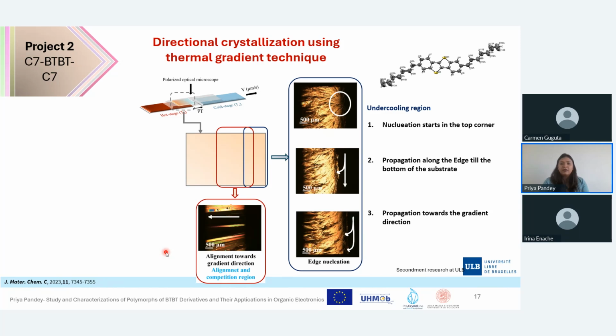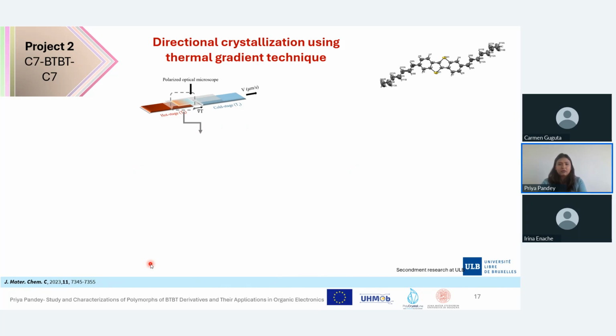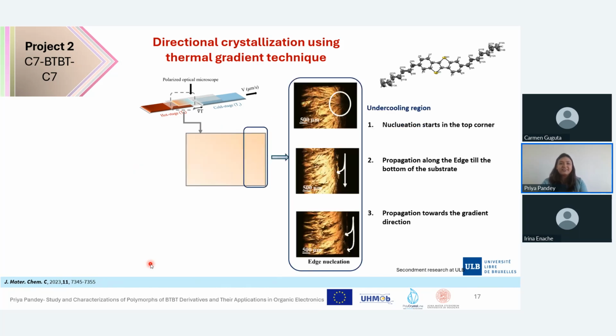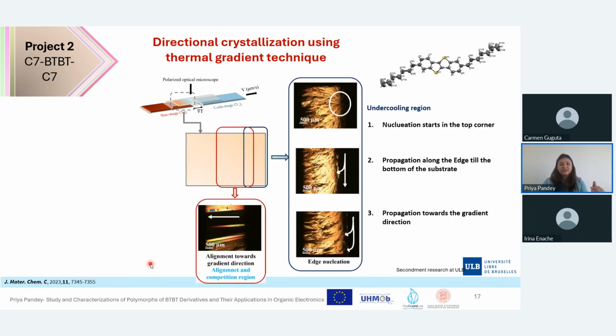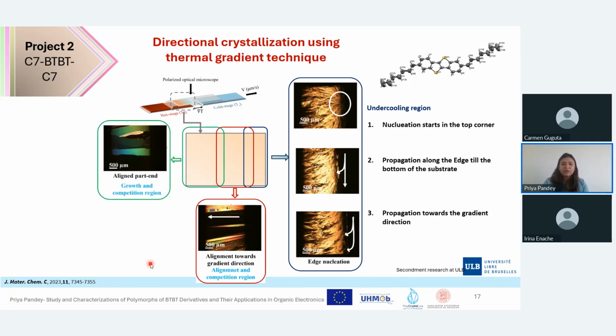Then comes the alignment and competition region. You can see the crystals are more aligned towards the gradient direction and much cleaner. Basically, this lies in the middle, where the crystals are in constant competition with each other to reach the growth front faster. In the end, we have the growth region where the growth front has been formed, and we can see much bigger domains of the crystals.